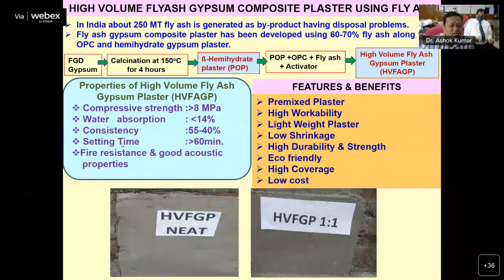The major properties of this plaster are compressive strength of more than 8 MPa, water adsorption of less than 14%, and consistency of 40 to 55%. The major features are that it is a premix plaster, with high workability, lightweight, low shrinkage, and high durability. It can be used as a single coat plaster or as a mortar by addition of sand.